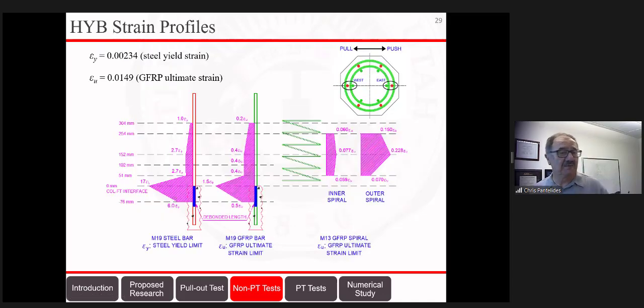This is also shown by this graph, which demonstrates the strain in the bar. So you can see that we exceeded the yield limit for these bars for the hybrid column, up to 17 times the yield. And for the fiberglass, we exceeded up to 1.5 times the ultimate strain, because at that point, of course, we had a fractured bar. And as far as the fiberglass spiral, we didn't actually reach more than 1/4 of the ultimate strain of the fiberglass, which means our design was efficient and it didn't go higher than that. Of course, buckling caused some of the fractures of the spiral.